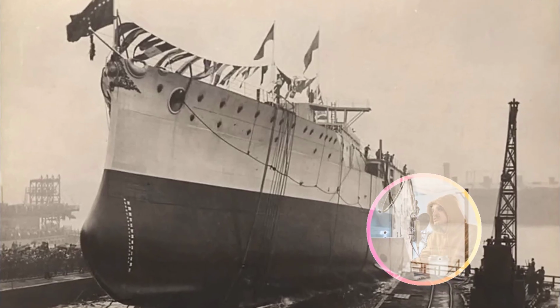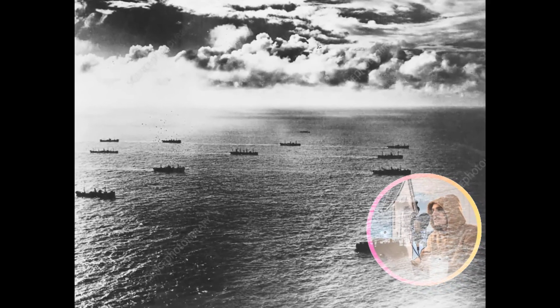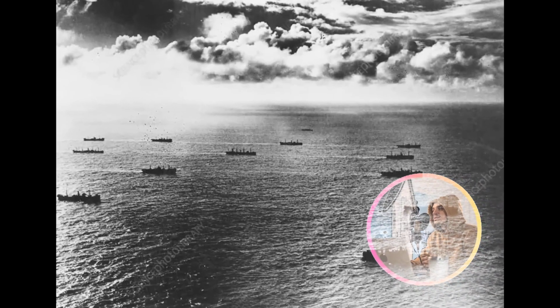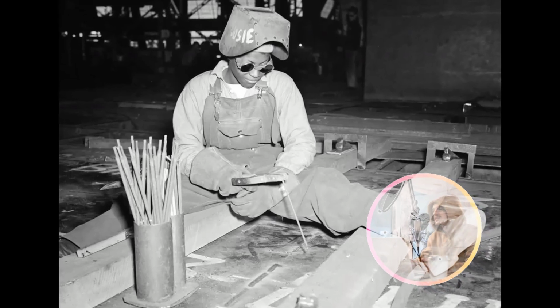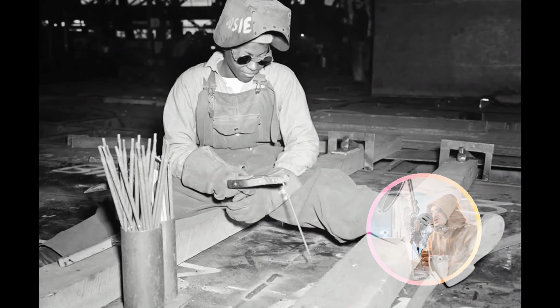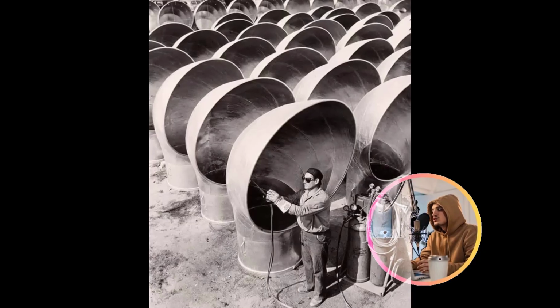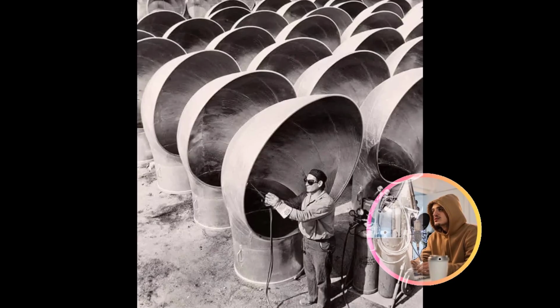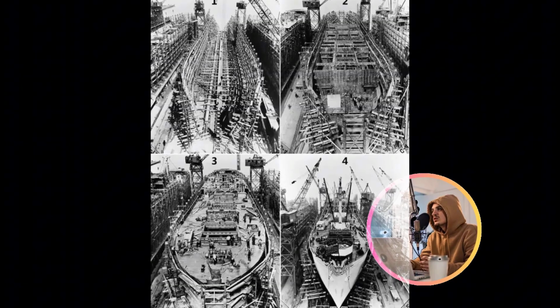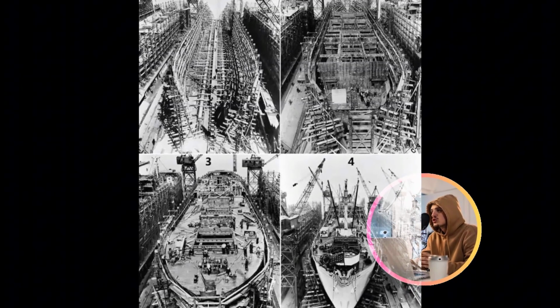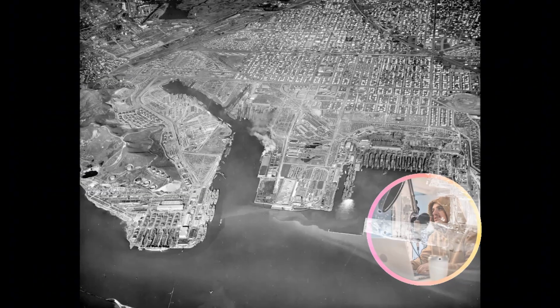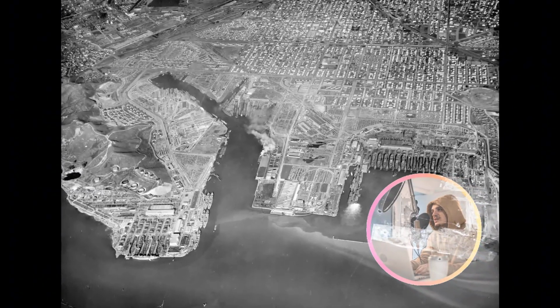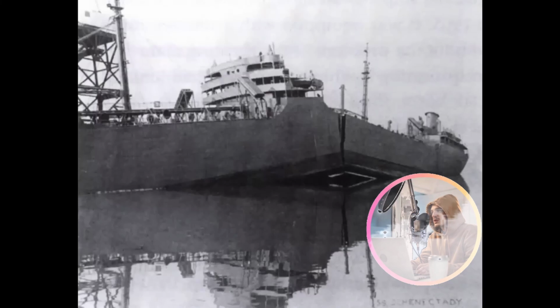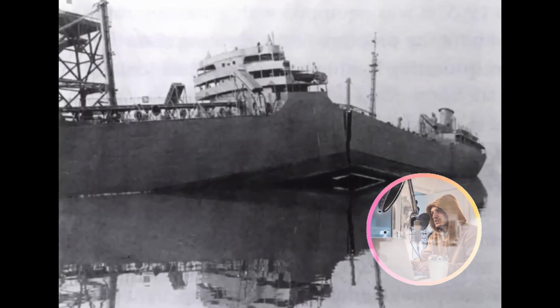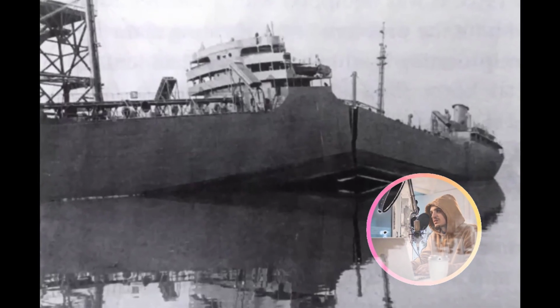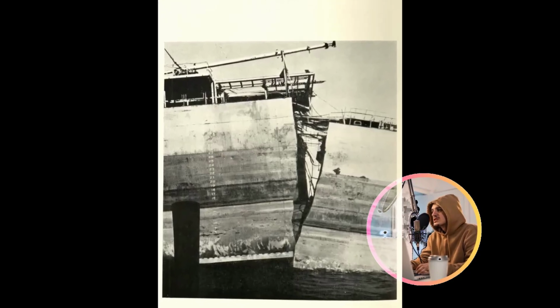The underlying physics responsible for these catastrophic failures finally achieved crystalline clarity. Steel is not a static, inert material. Rather, it possesses a dynamic crystalline structure that responds profoundly to fluctuations in temperature. When welders traverse a torch along a seam, they induce a localized temperature exceeding 2,500 degrees Fahrenheit. The metal within this heat-affected zone expands dramatically. As the weld subsequently cools, it contracts, but this contraction is powerfully constrained by the surrounding, cooler steel. The inevitable consequence is residual tensile stress, permanently locked into the structure, unless the welding sequence is specifically designed to facilitate the redistribution and dissipation of this internal tension.